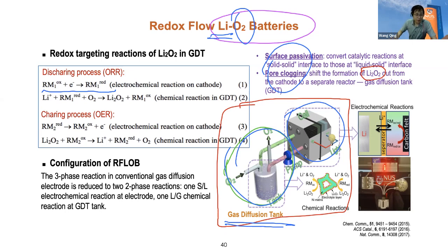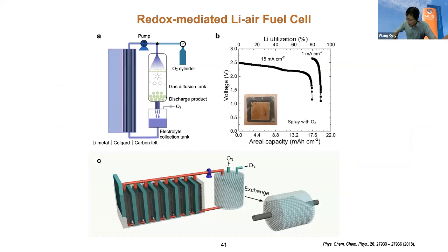So it can greatly enhance the depth of discharge. In other words, we can reduce the three-phase reaction in a conventional gas diffusion electrode to two-phase reactions. One is the solid-liquid electrochemical reaction on the electrode surface, and the other is the liquid-gas chemical reaction in a gas diffusion tank. With this, we can greatly enhance the power of the lithium oxygen battery. Look at here. We have the lithium electrode in the cell, and the reaction of oxygen is inside the separate tank here. We use the molecules quinone and viologen with the spray of the electrolyte, so the reaction can be greatly facilitated. So it can operate at a current of 15 milliamperes per square centimeter. For a lithium oxygen battery, this current is really high.